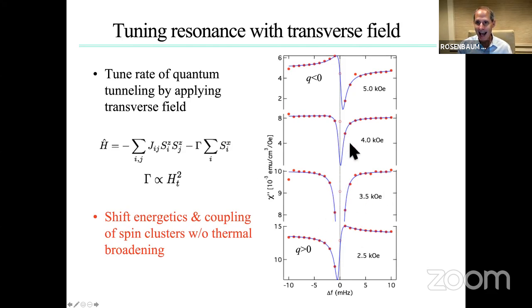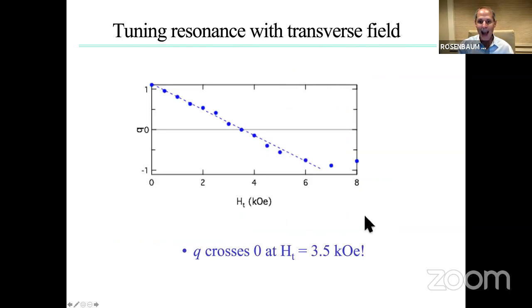The other thing I want to point out is, you remember when we just did temperature, the major effect was to broaden the line shape, right? We were melting it, we were smearing it. You can see here, as you move the transverse field, the line width stays very sharp. So there's no broadening here. There's no thermal effect. So this is purely a quantum mechanical effect. And so this is Q mapped out for a series of transverse fields. I just picked out those demonstration plots to show you the evolution. It effectively seems to go roughly linearly through 0, with 0 at about 3.5 kilogauss. And I'll discuss this in a little more detail in a second.